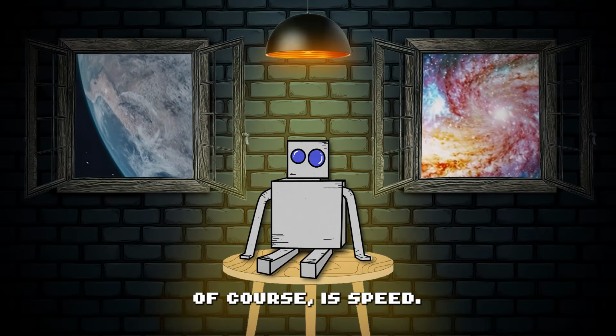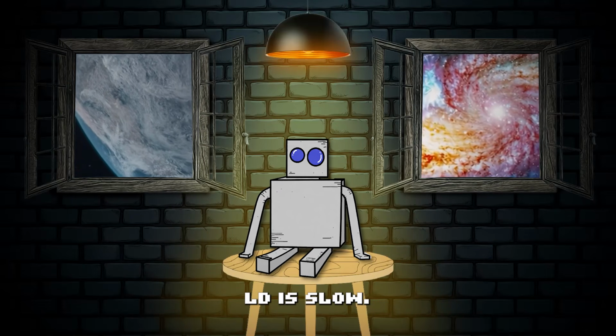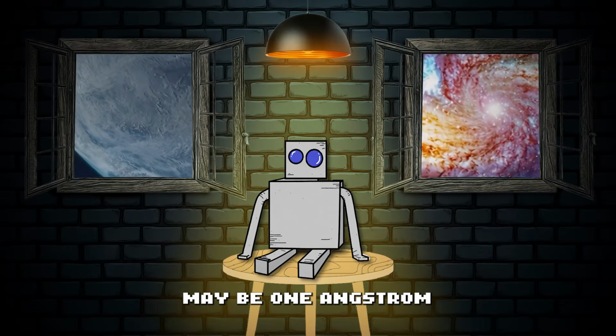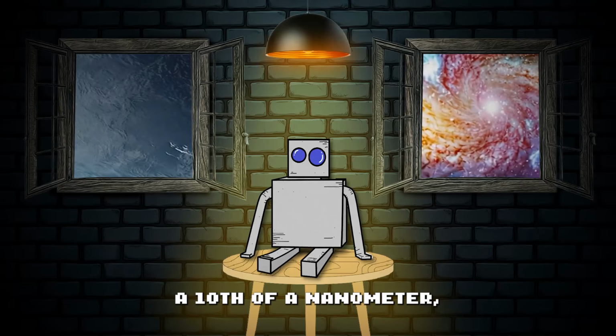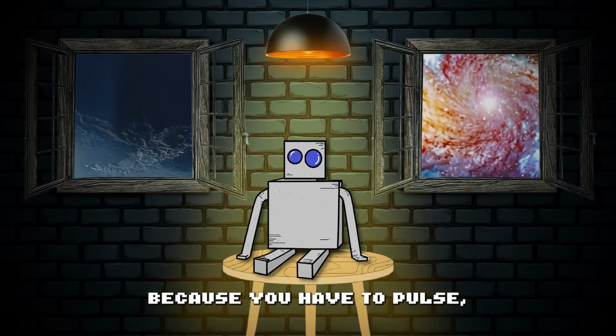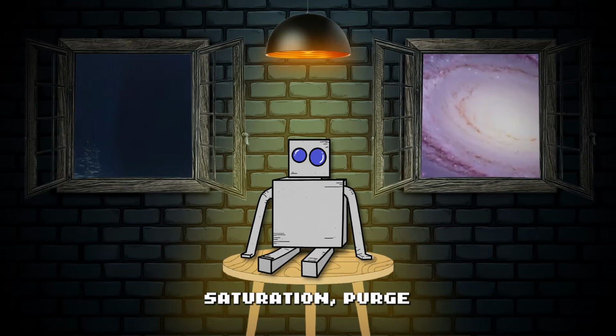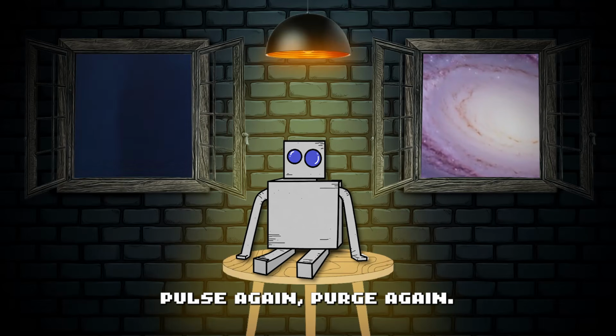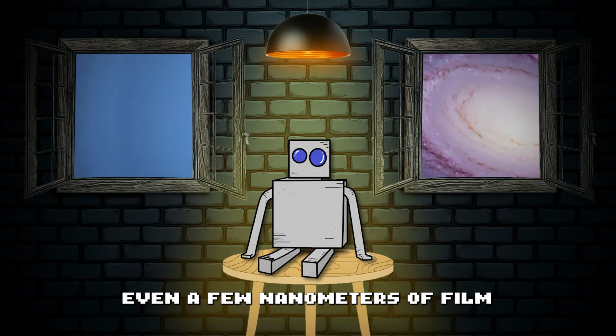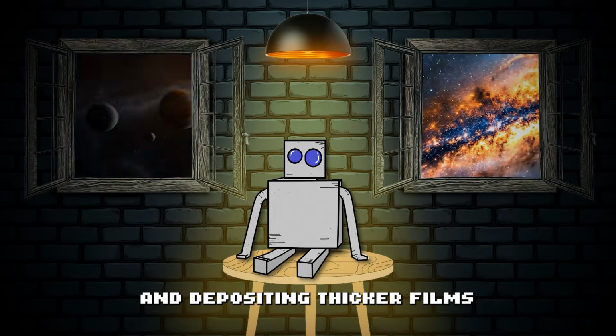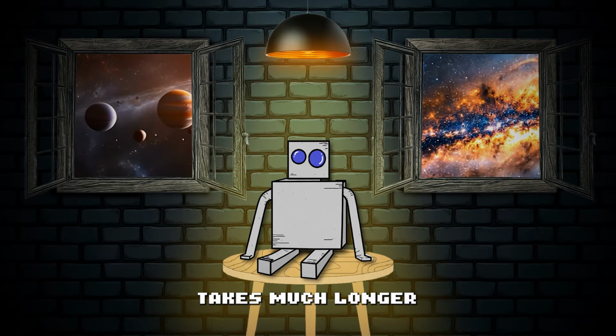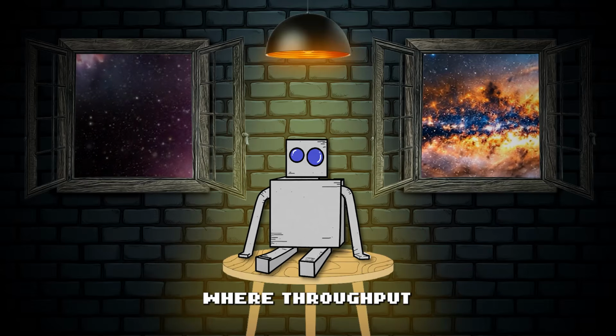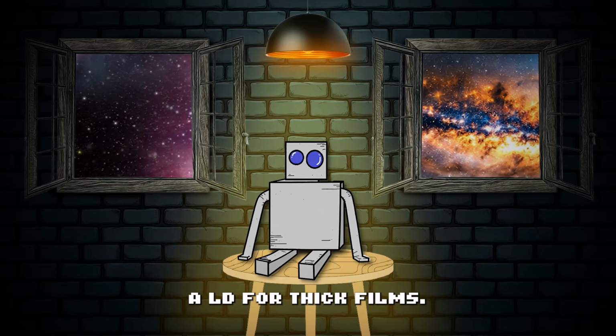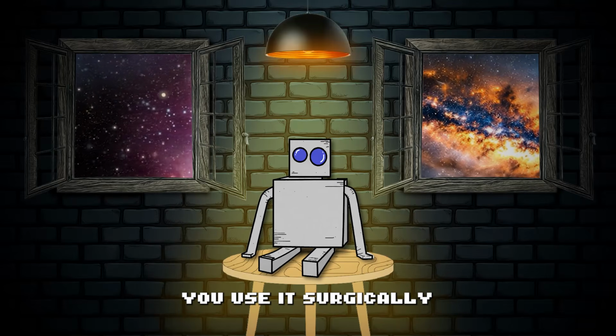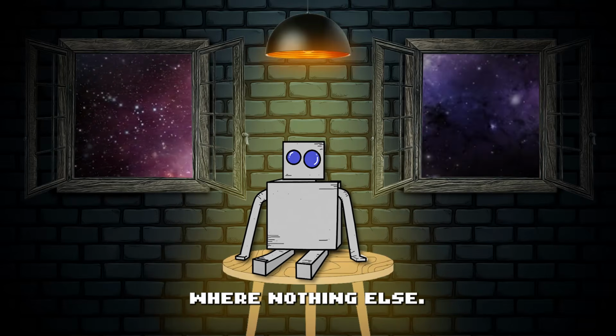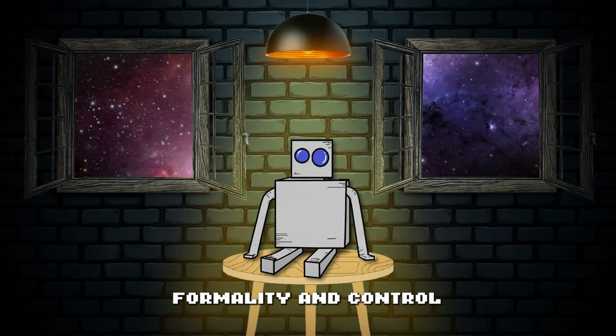The trade-off, of course, is speed. ALD is slow. Each cycle deposits maybe 1 angstrom of material, 1/10 of a nanometer. And each cycle takes several seconds because you have to pulse, wait for saturation, purge, pulse again, purge again. So depositing even a few nanometers of film can take minutes, and depositing thicker films takes much longer. For high-volume manufacturing, where throughput is everything, you don't use ALD for thick films. You use it surgically for the critical thin layers where nothing else gives you the conformality and control you need.